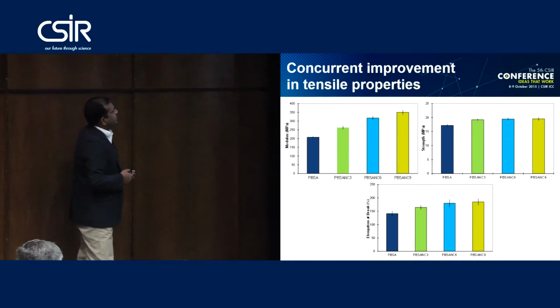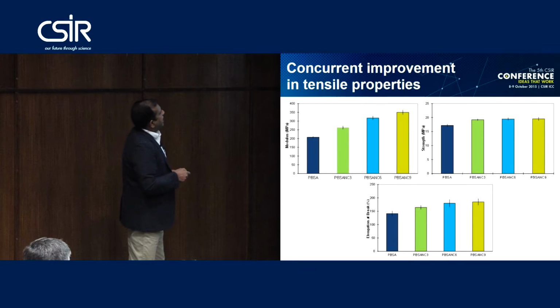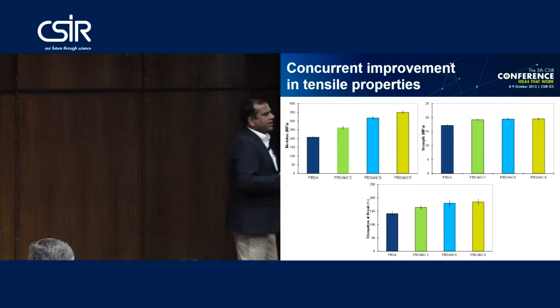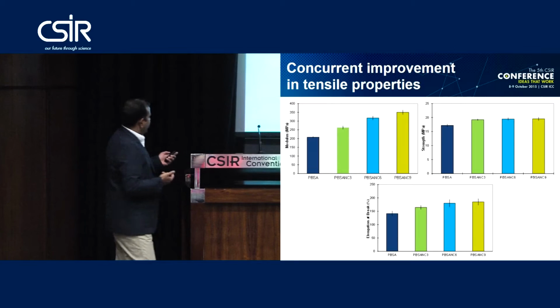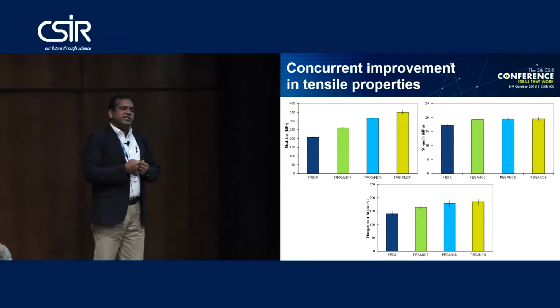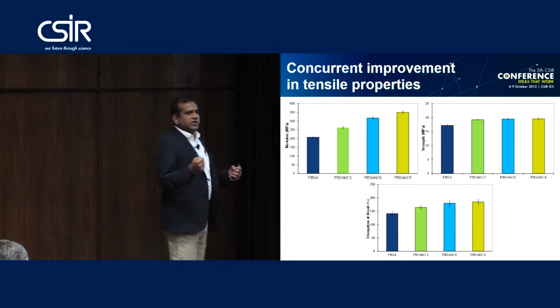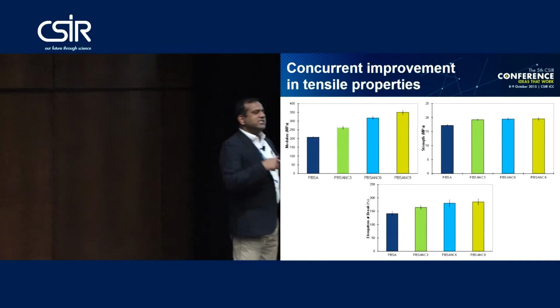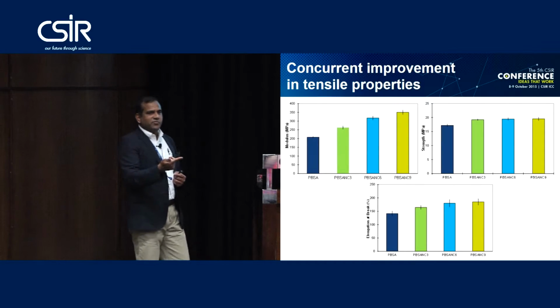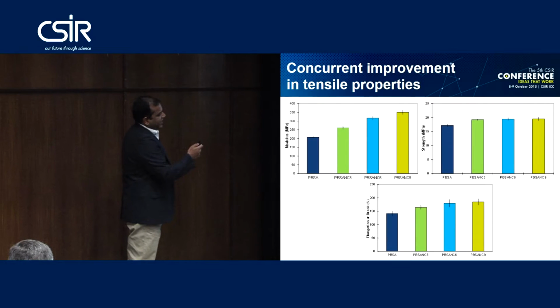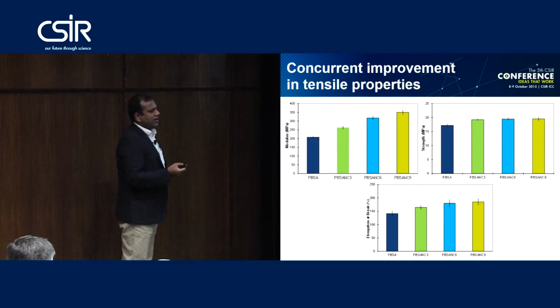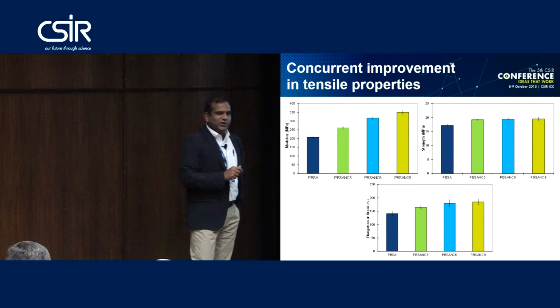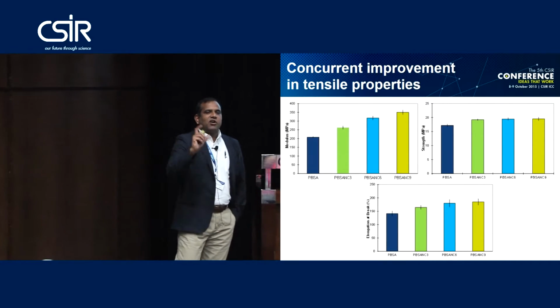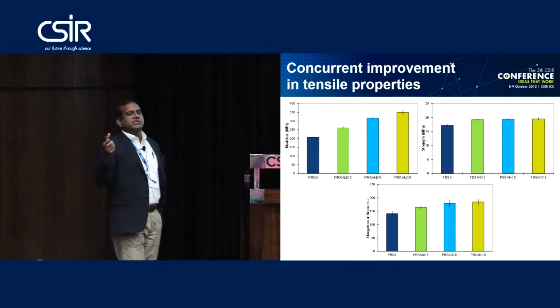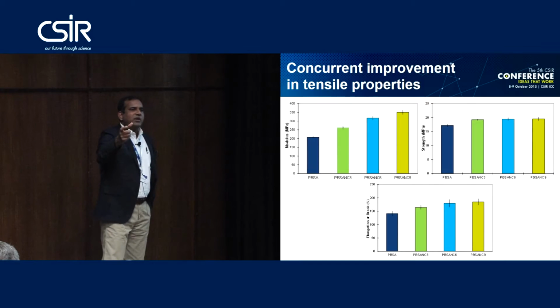What we are trying to do is incorporate nanoclay particles inside the polymer matrix, and we are not only improving the mechanical properties of the matrix, we are also improving its toughness. This is the unique feature of nanocomposite technology. You are not disturbing the inherent properties of the macromolecules. And why is this happening? Because you are adding a very, very low weight percent of clay platelets inside the polymer matrix. In conventional composites, you need almost 30 to 40%, sometimes even 50% of filler to get a certain level of mechanical properties.